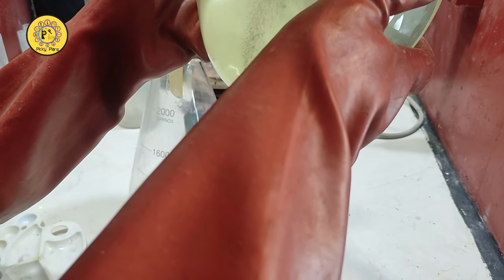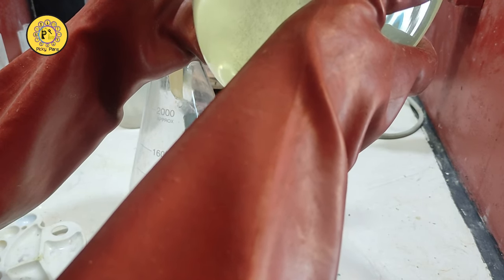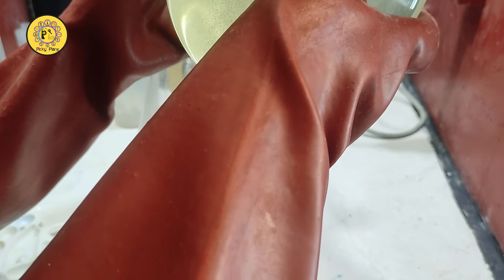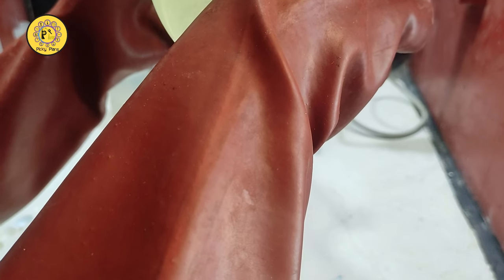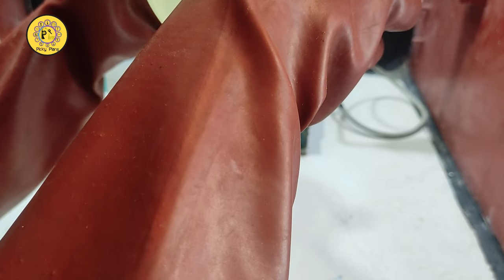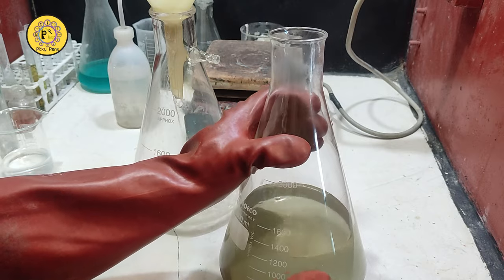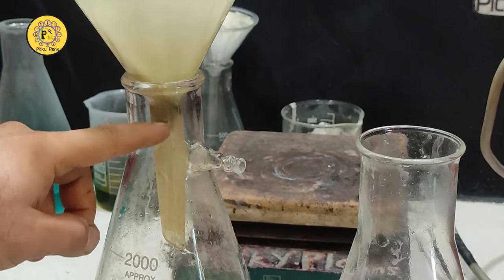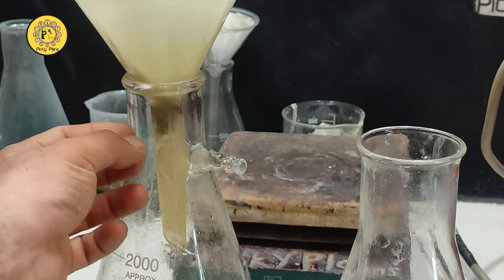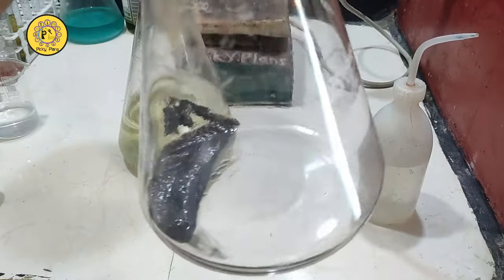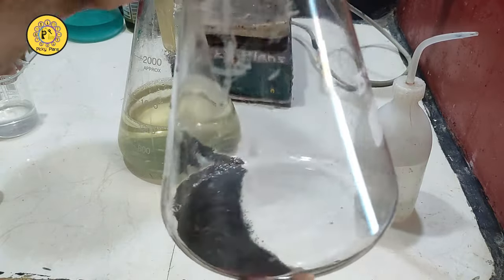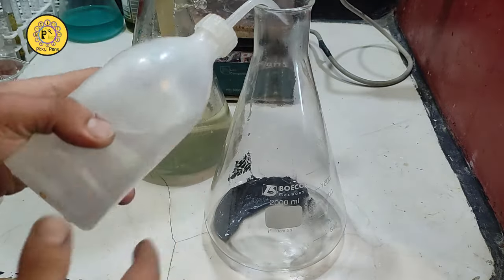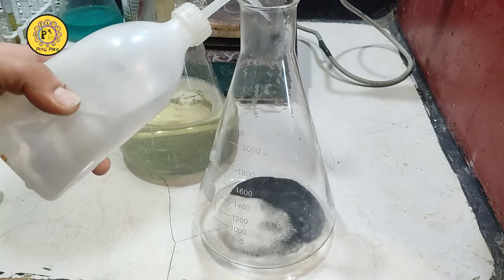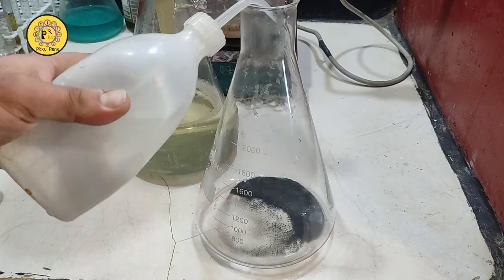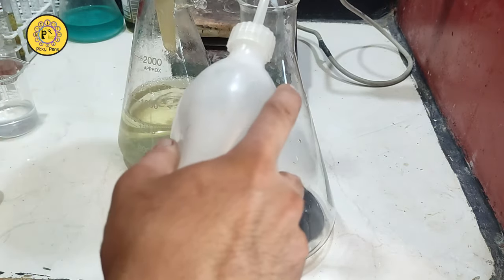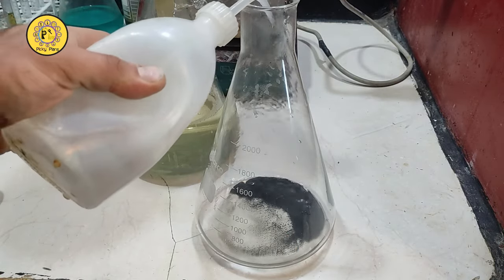Now process the zinc at the bottom for the gold. Washing step is very important to get rid of all alkaline solution before acidifying the solution to digest the zinc powder. As you can see here, there is some zinc and gold floating in the solution. It's trapped here. Right here we have a dark zinc cement with a fluffy appearance. This needs to be washed prior to adding acid to it. Just lightly being washed, just in case to not form any byproduct contaminating the gold powder.